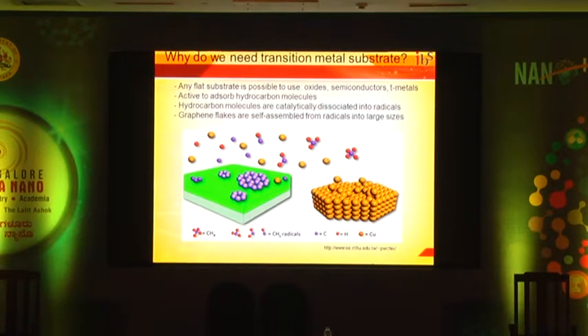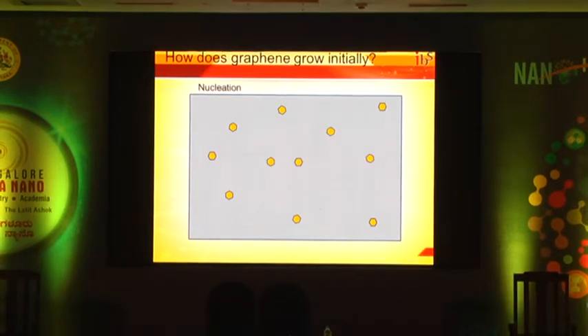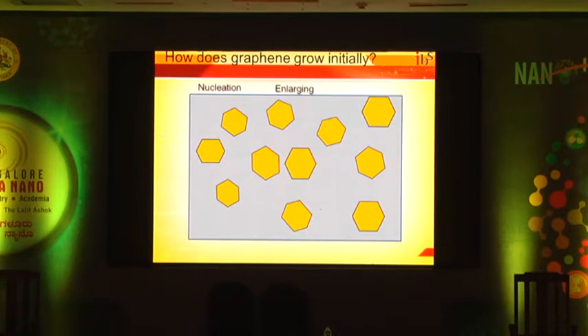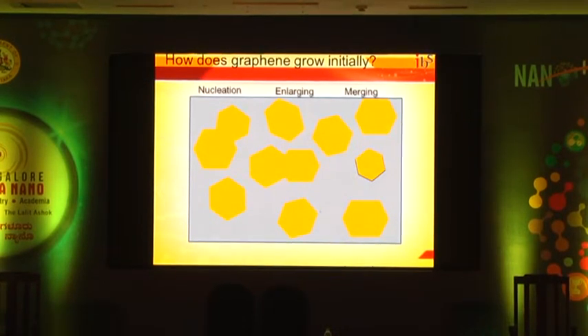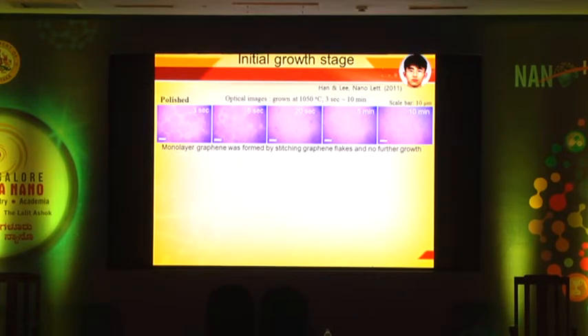So the idea of CVD, chemical vapor deposition, is very simple. You have a substrate, which is a transition metal that acts as a catalyst for decomposition of hydrocarbon gases. If you simply supply these hydrocarbon gases at relatively high temperature, like 1,000 degrees Celsius, you can decompose them easily, and you can deposit carbon on the substrate. So that's the idea. When you imagine this, of course, the nucleation seeds are not so easy to control. So they can start randomly from everywhere on the substrate, and then they start growing to larger sizes. Eventually, they meet together and form grain boundaries, which are the source of electron scattering and make high resistance. So the question is, can you really control this grain boundary? Without having grain boundaries, can you merge them together? This is the idea. So here, this is an example.